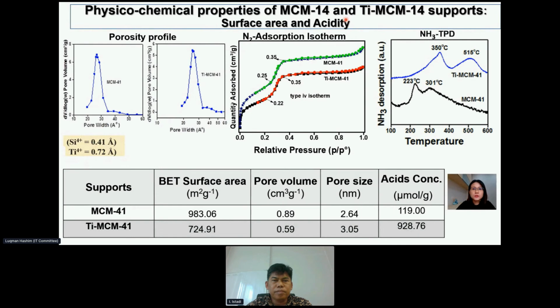Okay, so for the surface areas, it is found that the MCM41 shows a better and higher surface area as compared to the modified MCM41. Also, this is due to the collapse of the mesoporous structures of the MCM silicate structures once there's incorporation with a denser titanium species.